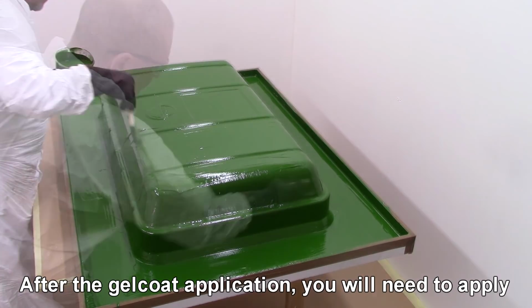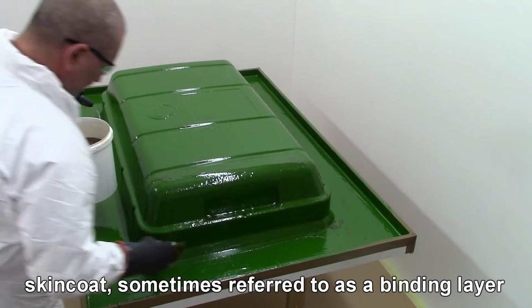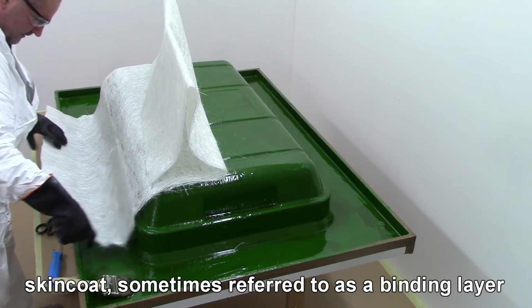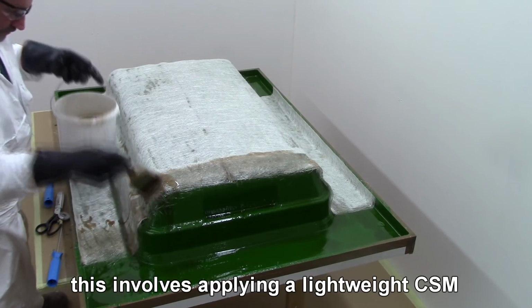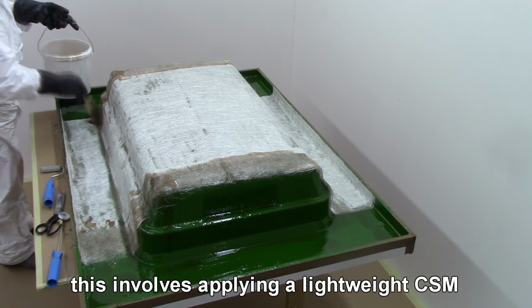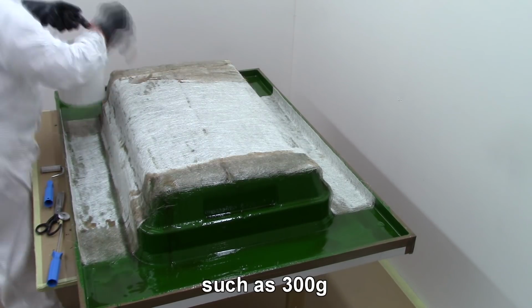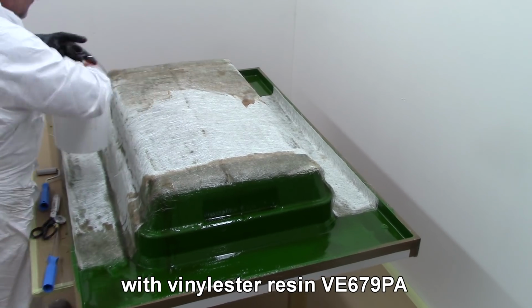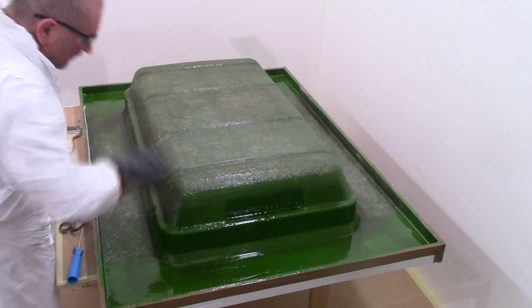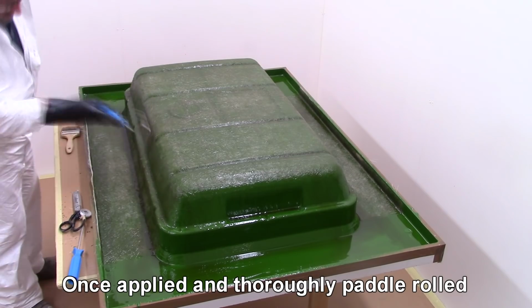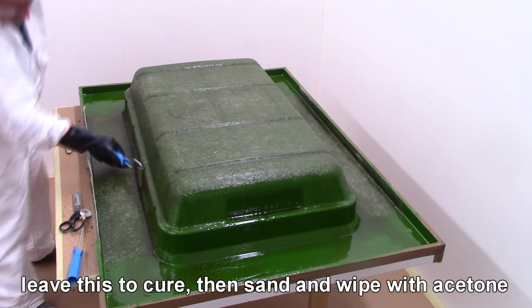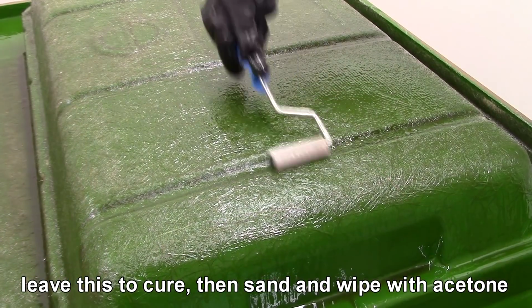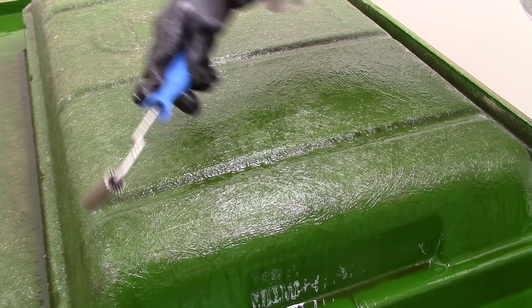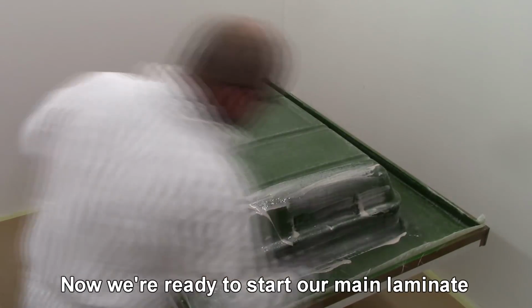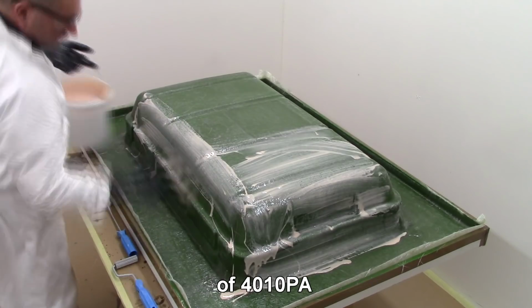After the gel coat application, you will need to apply your skin coat, or sometimes referred to as a binding layer. This involves applying a lightweight chopped strand mat such as 300 grams with vinyl ester resin VE679PE. Once applied and thoroughly paddle rolled to remove any air, leave this to cure, then sand and wipe down with acetone. Now we're ready to start our main laminate 4010PA.